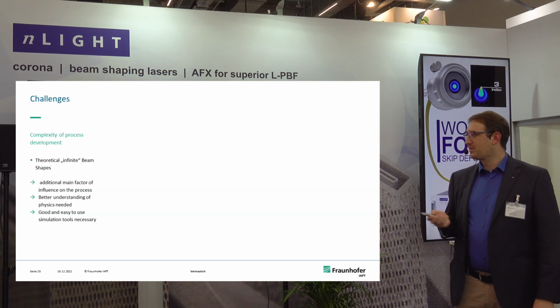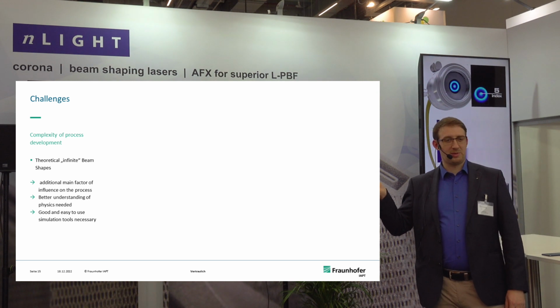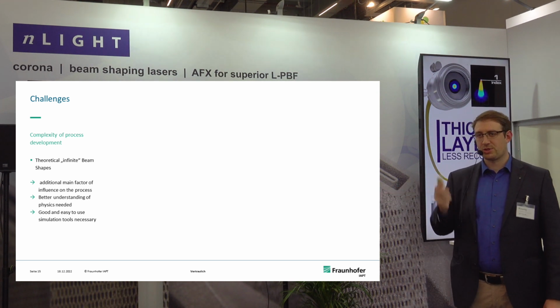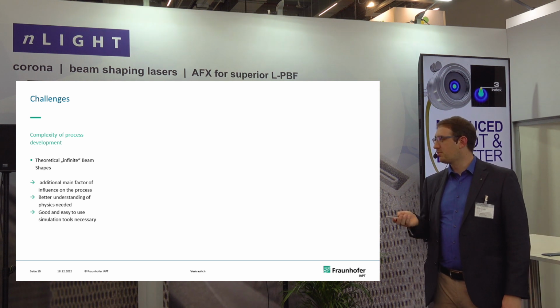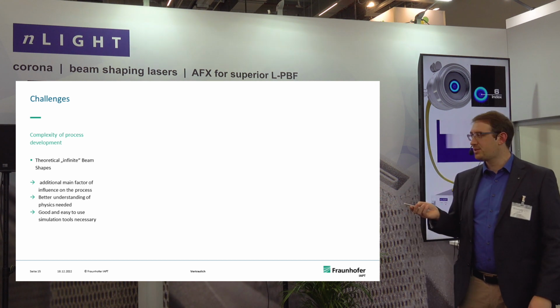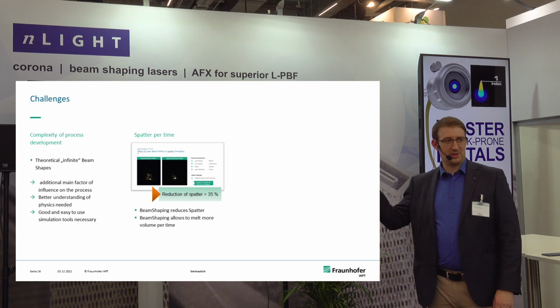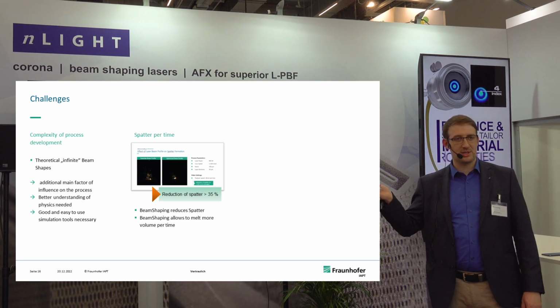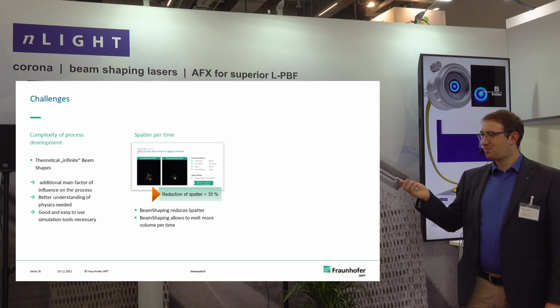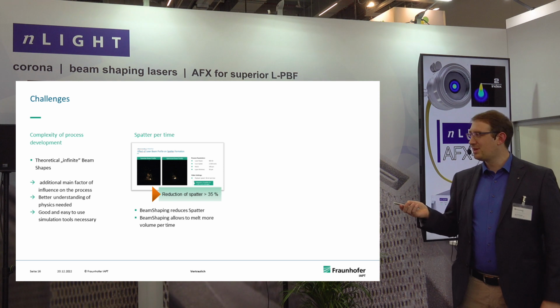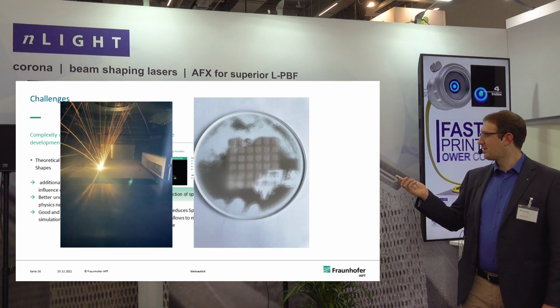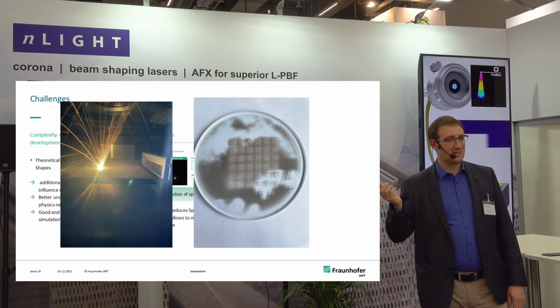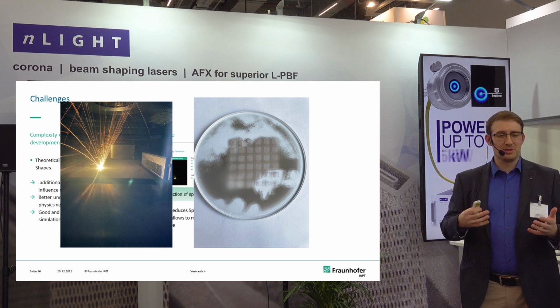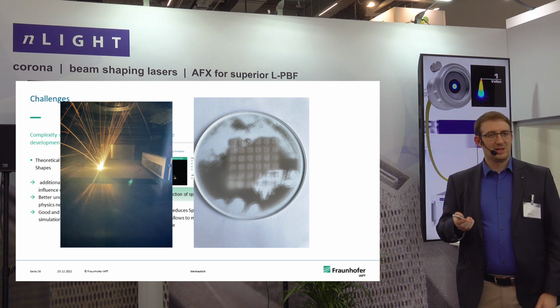I want to mention some challenges. We need to have a better understanding of the physics and also simulation tools, which were also presented here in talks before, because the complexity increases in the process development. I showed you the spatter slide where I mentioned that spatter reduces, but because we can melt more volume per time, we notice this. So this is a contradiction. But in the end, this is because we can melt more volume per time: per volume the spatter reduces, but per time, because we can be more productive, it increases.